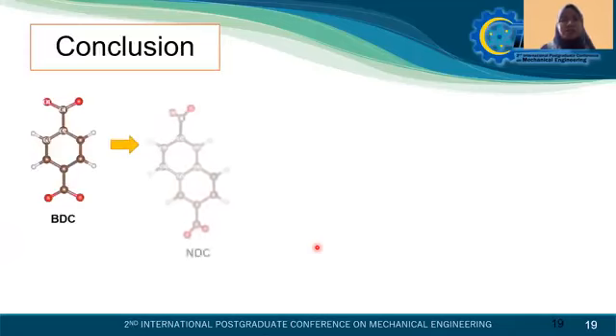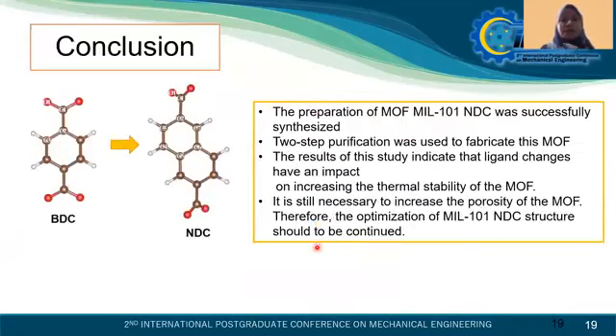So our conclusion is this one. After we do the ligand functionalization from the BDC into NDC, we have successfully synthesized this MOF, and it is evaluated by some adsorbent characterization. And we do this two-step purification to fabricate this MOF, and also the ligand change has an impact on the increase of the thermal stability of the MOF, because as you can see, compared to benzene dicarboxylic acid, naphthalene dicarboxylic acid has higher thermal stability.